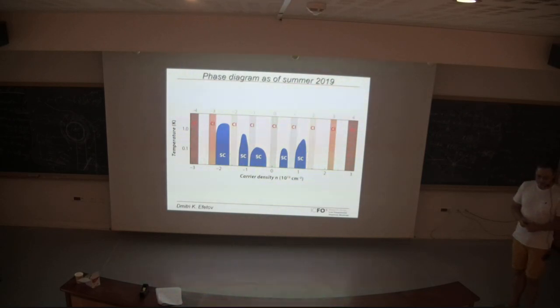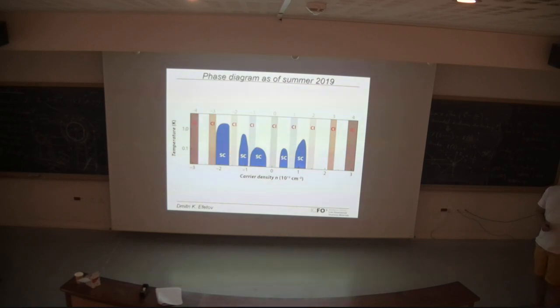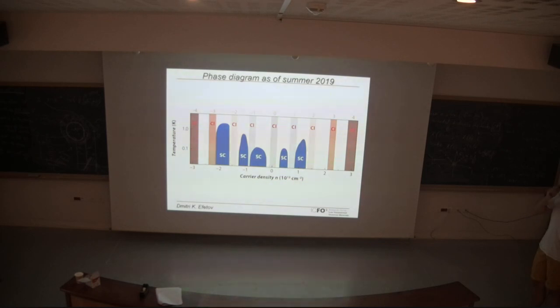Okay. So one thing I also want to say, this is more like an experimental fact, is why I personally believe that we really went from this picture to this picture now: because I think we are starting to make better and better samples with less impurities, less inhomogeneities. And actually this picture here is in principle consistent with the previous picture, where again the strongest insulating features which we observe are -2 and +2, and the superconductor is close to -2. This is really consistent, so the energy scales are similar to what was reported before.